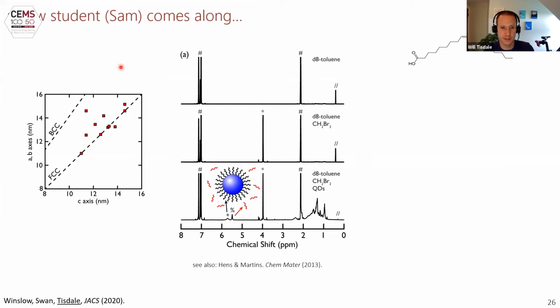He had the very good idea to check the proton NMR. So this is some example proton NMR. This is our deuterated toluene solvent. Then Sam does another collection where he adds some dibromomethane to the deuterated toluene, which acts as a quantitative standard so that he can quantify the number of protons that he's looking at. And then if he looks at the quantum dots in deuterated toluene with dibromomethane, he sees all of these aliphatic protons out here that are a big mess.